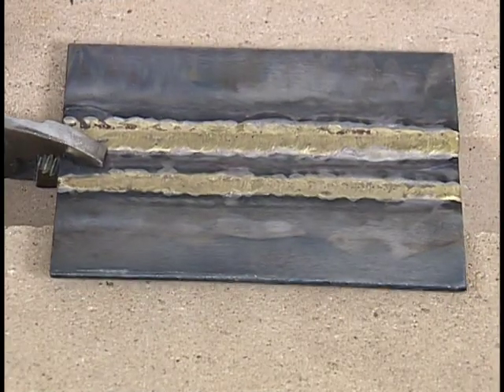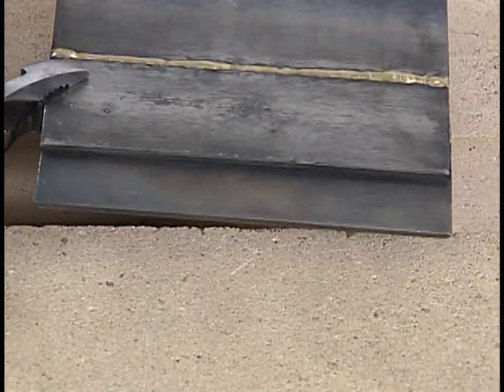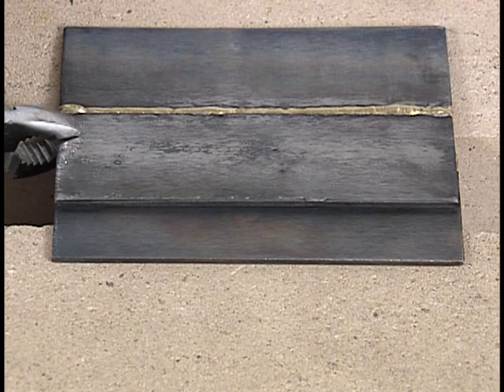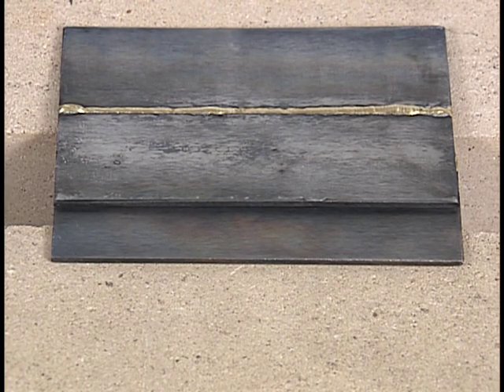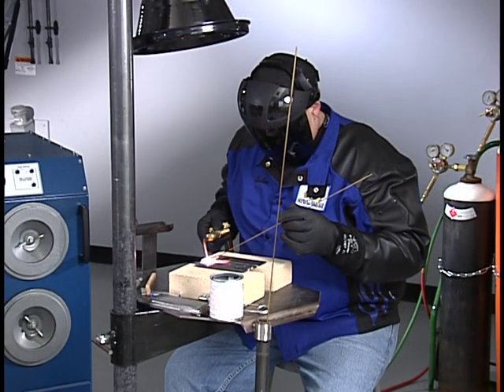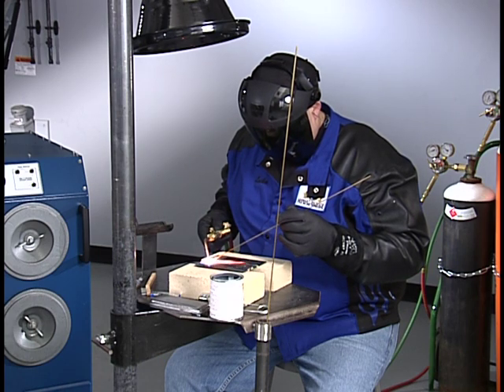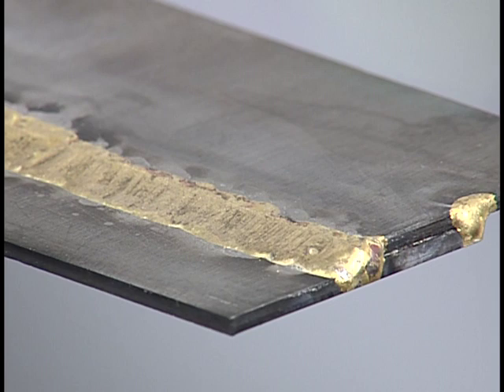Once you have completed the weld, allow the workpiece to cool briefly or switch to another workpiece. Flip the workpiece over and reposition it so you can weld the lap joint on the opposite side. Deposit the fillet weld using the same techniques as before. Be sure to maintain consistent work and travel angles as you move along the joint. The finished weld should be flat to slightly concave, bonding thoroughly with the surfaces and edges of the joint. Inspect your welds and continue practice.